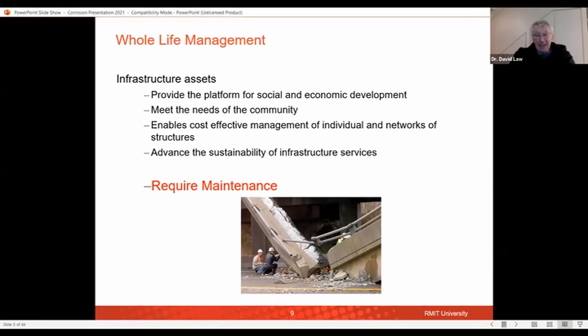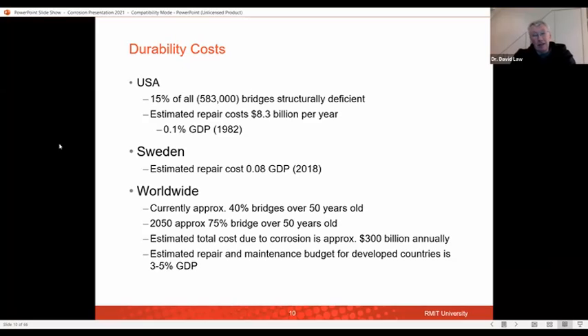And if we have failures in this infrastructure, it's going to be a major cost to repair, but also a major disruption. So even if there are no fatalities, and the illustration there was a collapse overnight due to corrosion in the bridge, which had been caused by de-icing salts being applied on the surface, not an issue that you would have in Sri Lanka. But obviously in Sri Lanka, there are other issues with regard to it being an island and much of the infrastructure built in a marine environment where you've got the chlorides that can get in and cause deterioration. And obviously higher temperatures and high humidities can also drive that corrosion even faster. And it costs a lot of money.